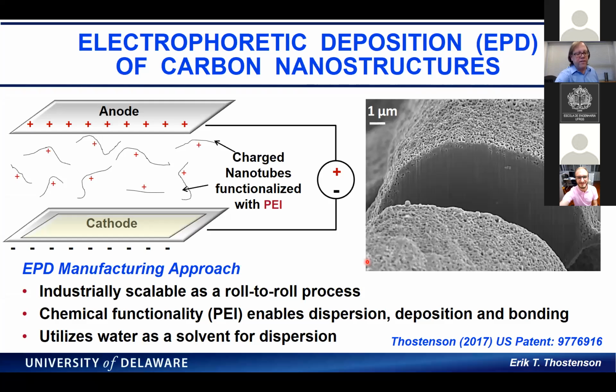So you can think, if we have two particles with the same charge, they're going to repel each other. But because we have charge, we can also utilize that to move the particles. And again, of course, opposite charges attract. So here, if we apply a potential, they will deposit on the cathode. In this case, we take a fabric and back it onto the cathode, and utilize that to deposit. And it's not just a physical deposition process, but it actually creates a very uniform coating. On the right-hand side, we've cross-sectioned a fiber, and what you see is this very uniform